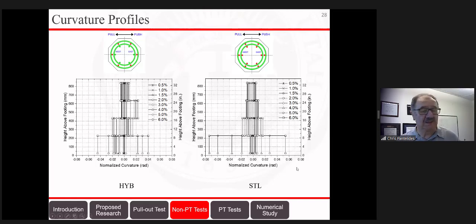And on the right, you can see the all-steel column. Basically, what you can see is that the all-steel column concentrates all the curvature at the bottom 200 millimeters or so, which is very typical for all-steel columns because this is where the bars yield. And on the left, you can see that the fiberglass bars do not yield, which results in a more uniform curvature distribution along the column length.